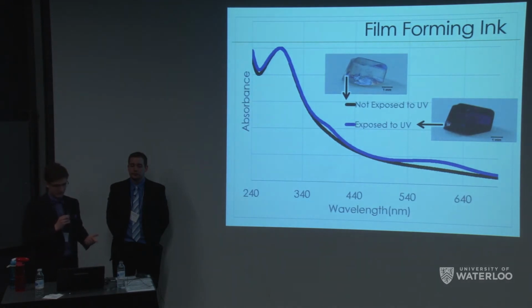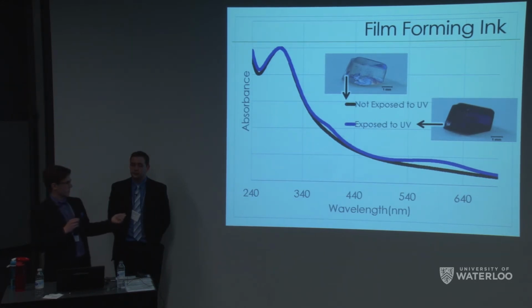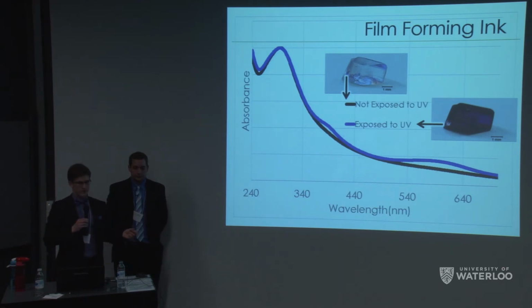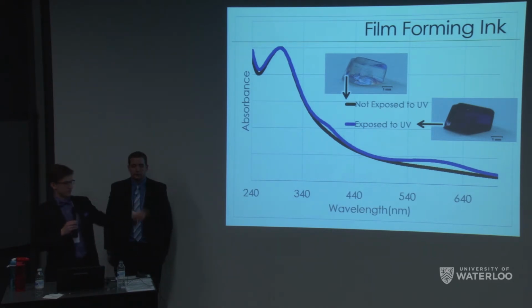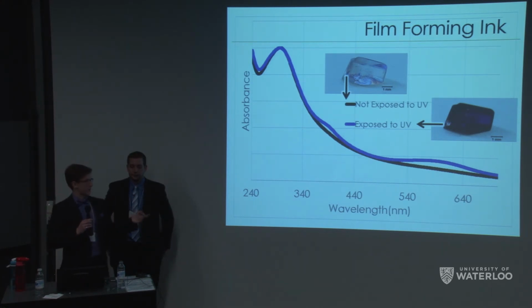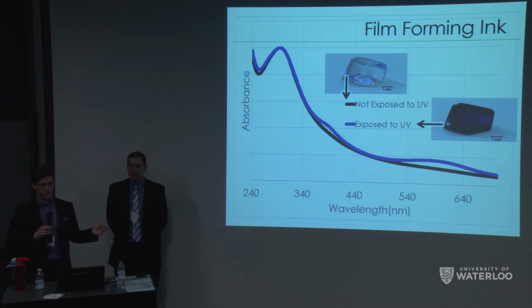And how has this affected us? So if you remember the UV spectrum from before, we had very defined peaks. But once we created our film forming ink, we noticed that our peaks are much less defined. However, you can still see that there is a strong absorbance in the UV range, which causes our ink to change color to purple. And once sunscreen is blocking the ink and you're exposed to both UV and visible light, the slight peak in the visible range allows the molecule to relax and to return to its clear state. And this happens in a very short amount of time.